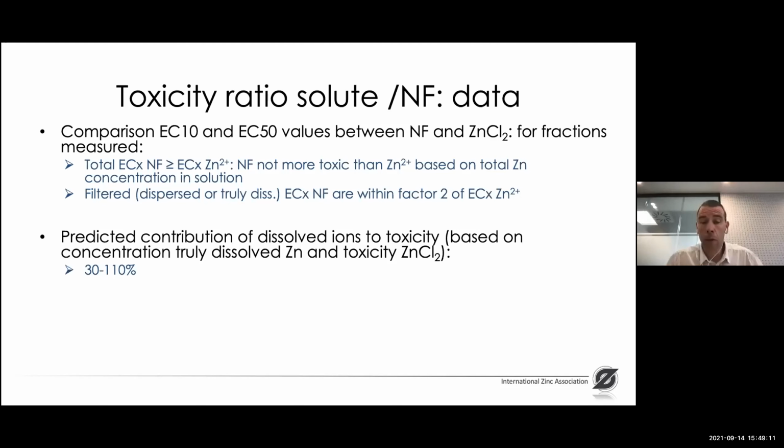Here I want to say that we found quite some uncertainty related to this comparison. First of all, we have the uncertainty related to the analytics: what we measure as the ions present in the nanoform solutions, is that a representative value, or is that an underestimate? There is also the uncertainty on the dose response curves. The further you go to the extremes of the dose response curves, the more uncertainty there is on the percentage effect predicted that you need for predicting the contribution.